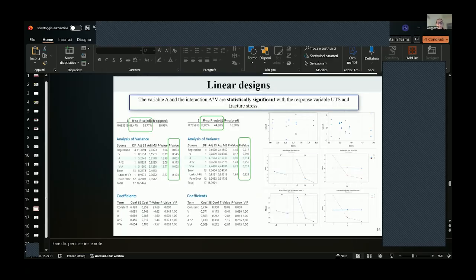And let's look now at ultimate tensile strength and fracture stress. Again, we have the statistically significant effect of angle alpha and the interaction of alpha angle and the vertex position, as is shown from both the ANOVA tables. And in this case, we have a quite good R and R squared for both cases, close to 70 and 60%, and from the main effect plots and interaction plots.